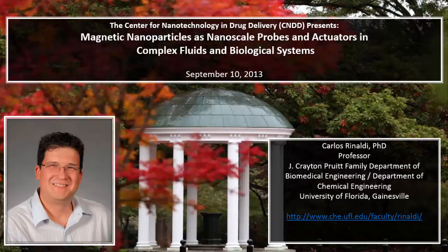So our particles are coated with a polysaccharide, carboxymethyldextran. They have EGF on the surface. The EGF is covalently bonded to the dextran. The dextran is covalently bonded to the particle, so they go with each other. They can't leave each other.